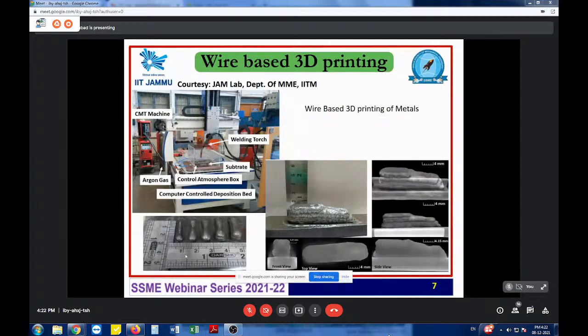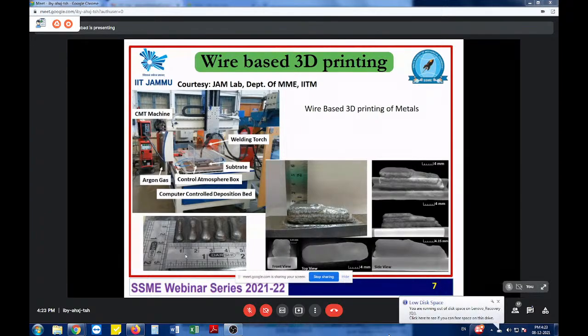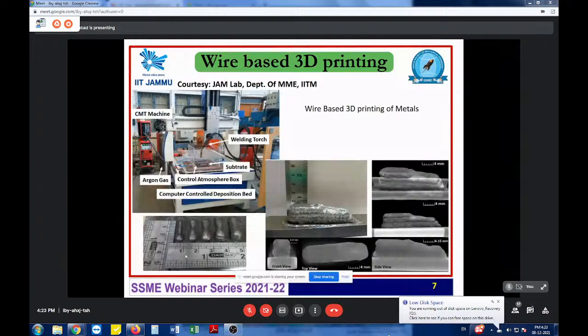Another interesting type of 3D printing I started working on during my postdoc is wire-based 3D printing, and this setup is about to arrive at IIT Jammu as well. In wire-based 3D printing we use metal wires with a welding source — here we used CMT (Cold Metal Transfer), a modern technology where unwanted heat distribution in the sample can be controlled. As a result, hot cracking has been controlled, surface-level wetting has been controlled, and very precise dimensions have been obtained in the 3D-printed components.